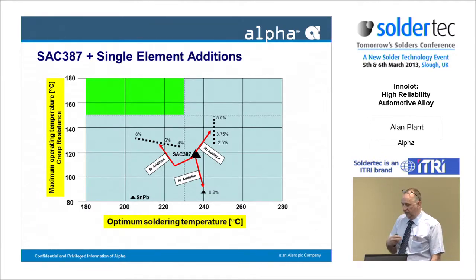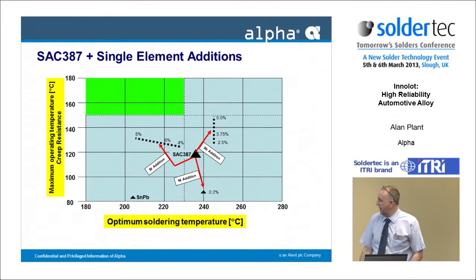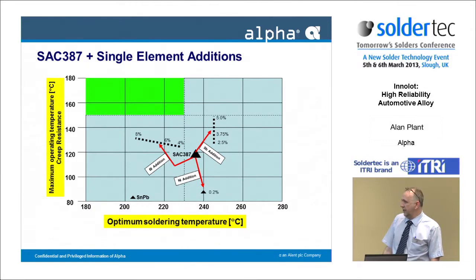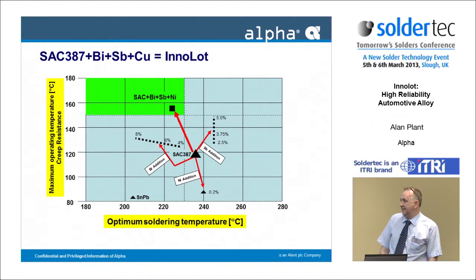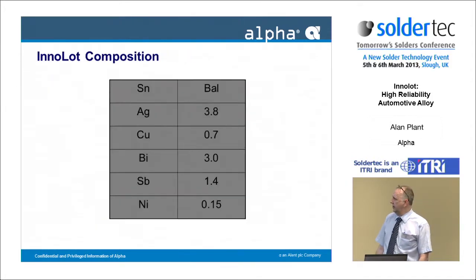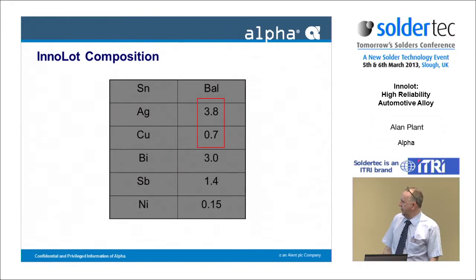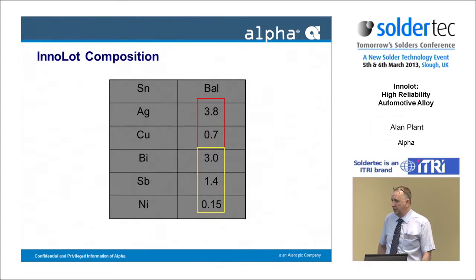So it came out that we couldn't just buy a one element addition, make a quaternary alloy that would fit the bill. So what they did was they looked at adding a multitude and came up with a 6-part alloy, which is quite a complex alloy, I guess, for a solder. And by making additions, there's a lot of work behind this, how much they added, to take us into this region, and they came up with a final Innolot composition of the 387 base alloy, 3% bismuth, 1.4 antimony, 0.15 nickel. Okay.